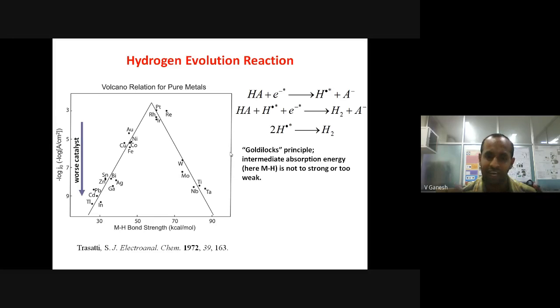Now, whenever you talk of any electrocatalysis process, the Volcano plot becomes very, very critical. This is a plot between current density versus the bond strength between the adsorbate and adsorbent, the hydrogen adsorption to metal, for example. And this provides information about the compromise you need to make between adsorption and desorption. Okay. Platinum is a well-known electrocatalyst because it displays a very high current density for an electrocatalytic process with very low bond strength, kilocalories per mole, meaning it requires very little energy and gives a higher amount of catalytic activity. The next best we have are rhodium, iridium and rhenium.